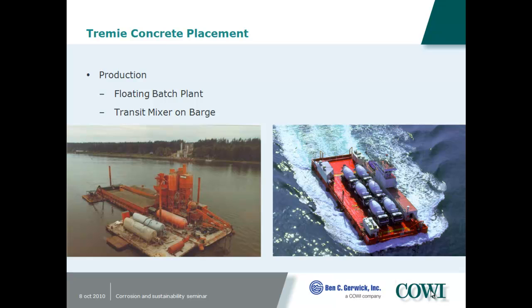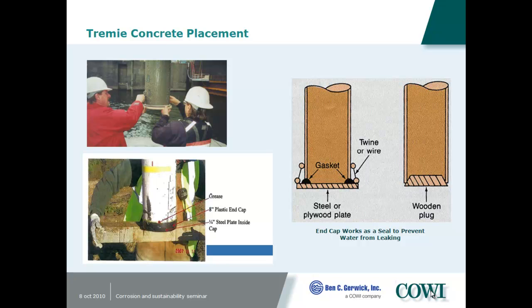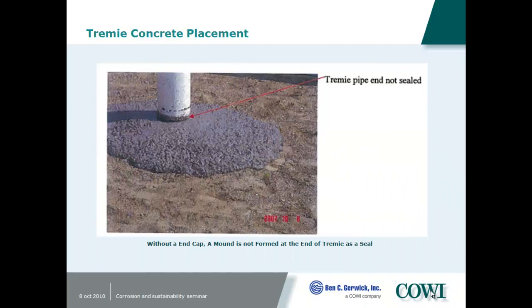These are just different ways of getting the concrete to the site. You can either have a floating batch plant or take it by a transit mixer, or in this case they actually wind up pumping it through a pump line to an agitator and then placing it down the line. You have to start off the placement with different ways of sealing the Tremie pipe, either with a cap or a plate, or you can also use a pig, but here we're using a plate on the end with tie wire. So this just shows it getting started.